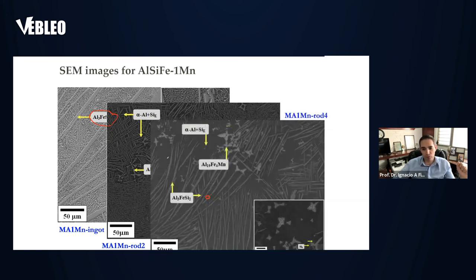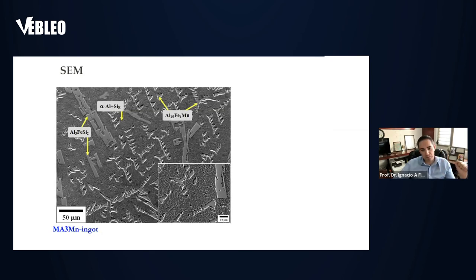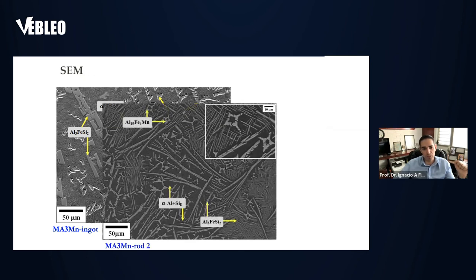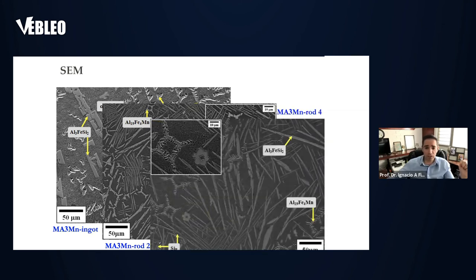When we increase the amount of manganese, the intermetallic with manganese increases and we still have the acicular structure problem. With 3% manganese in the ingot, moving to the rod the large plates become slightly thinner but sharper and move in different directions — we think this may stop the movement of dislocations, thereby preserving the plastic deformation of the alloy. For the 2 mm rod and the 4 mm rod we also found a rosette structure — a new microstructure for this kind of alloy produced by rapid solidification.